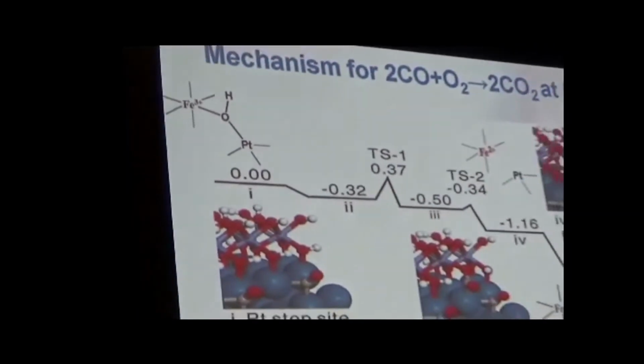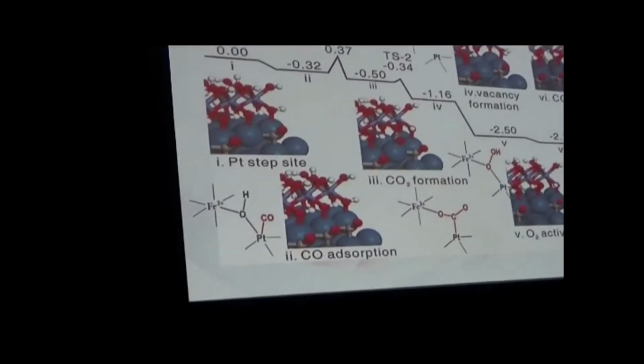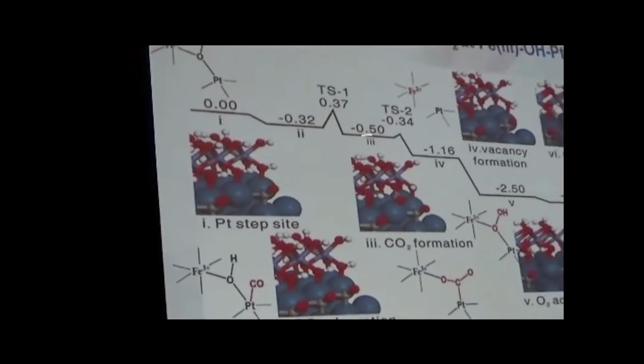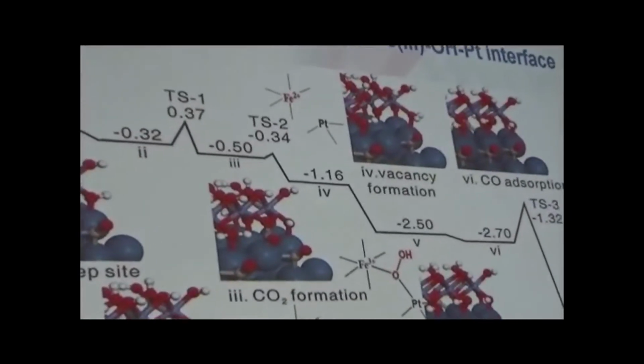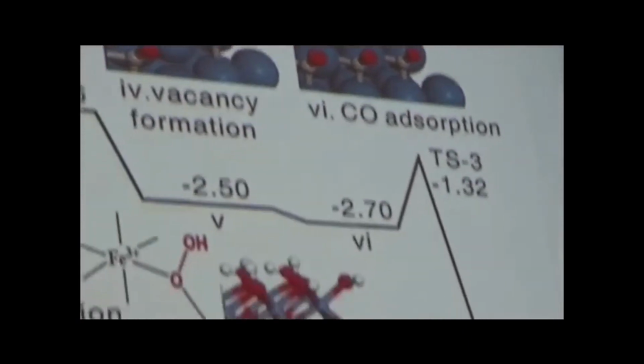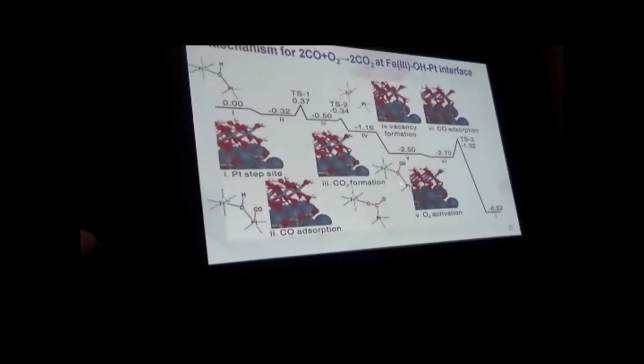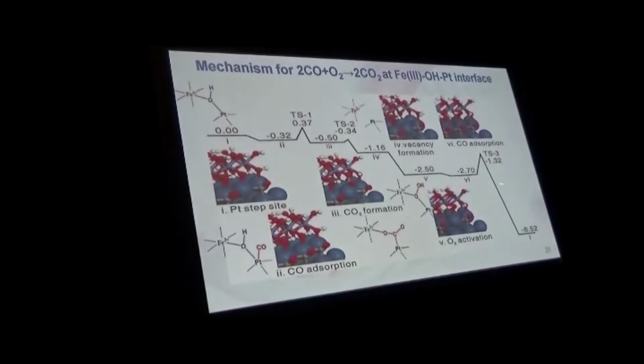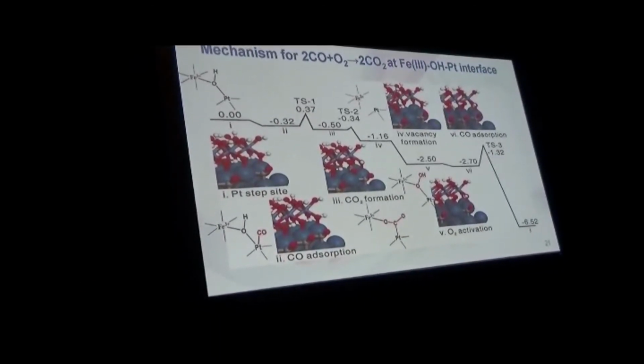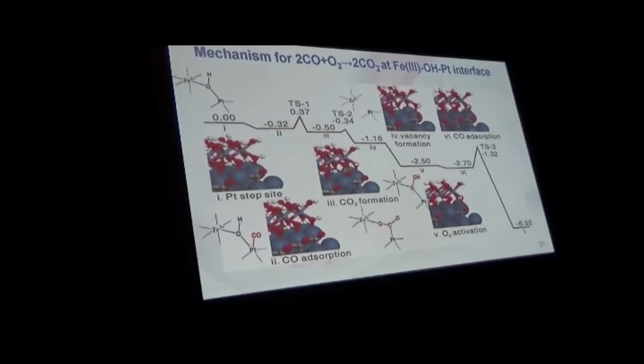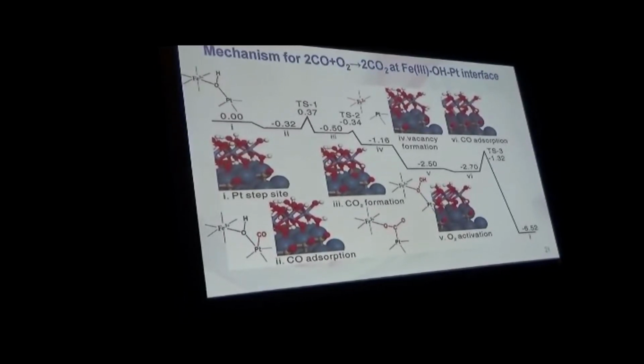How to create the vacancy? In our mechanism, the vacancy can be created in situ. In the first step, we have the iron hydroxide on platinum as the interface structure. Here, CO adsorbs on the platinum. It can react with the OH to give COOH, and then COOH loses the hydrogen to give CO2 and generate a vacancy here. And such a vacancy is able to activate the oxygen. So we get the OH species, and the second CO will react with the OH species to make another CO2 and recover the interface structure. So we complete the catalytic cycle.